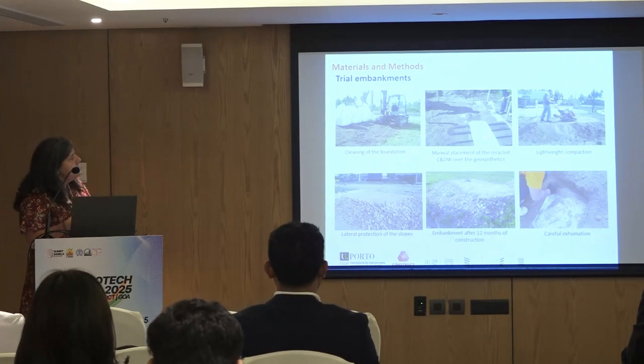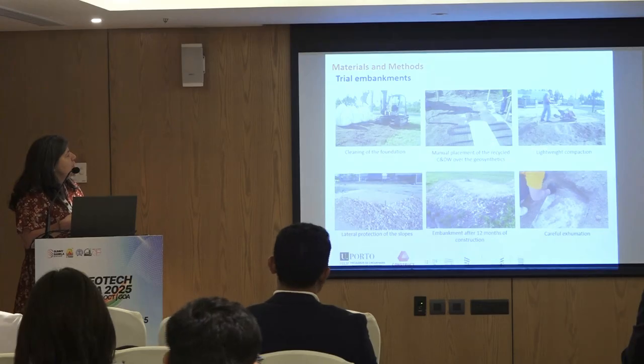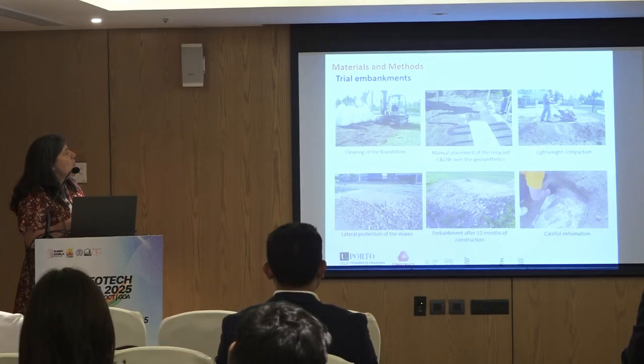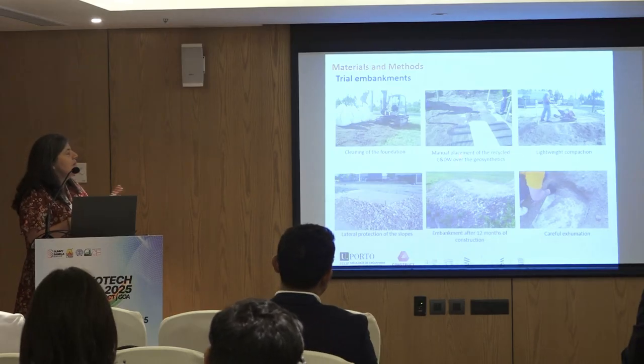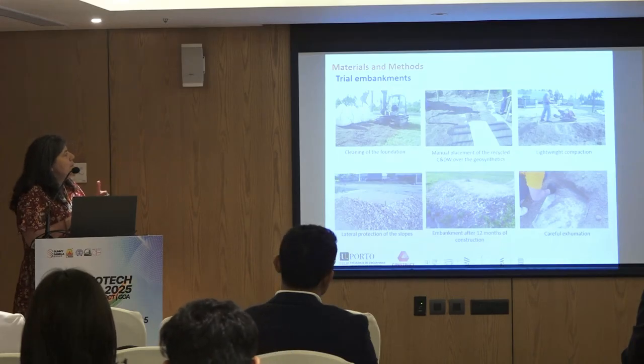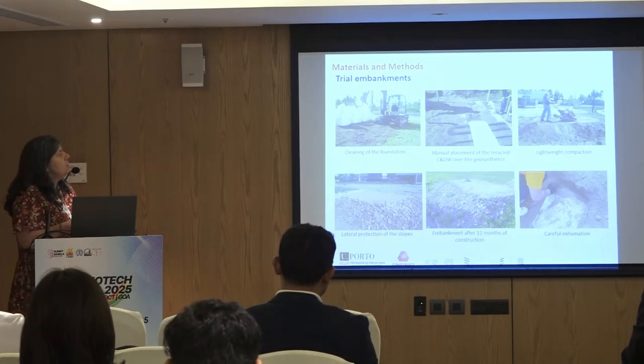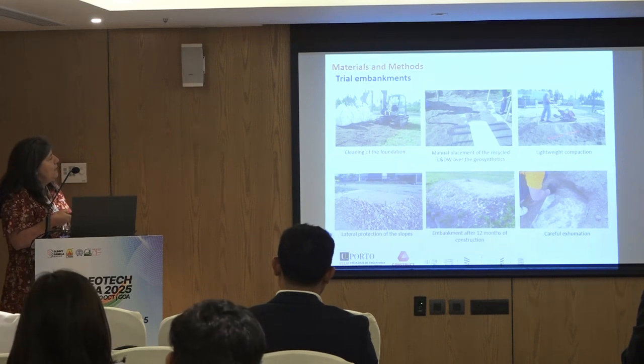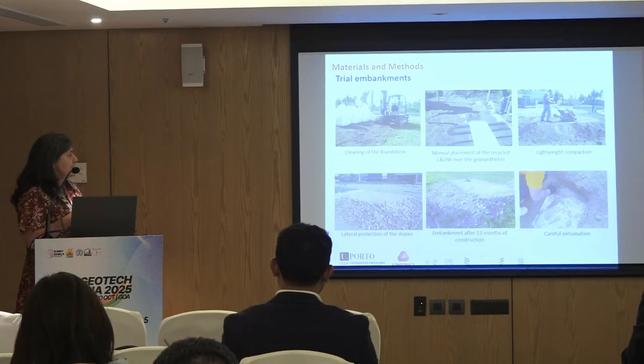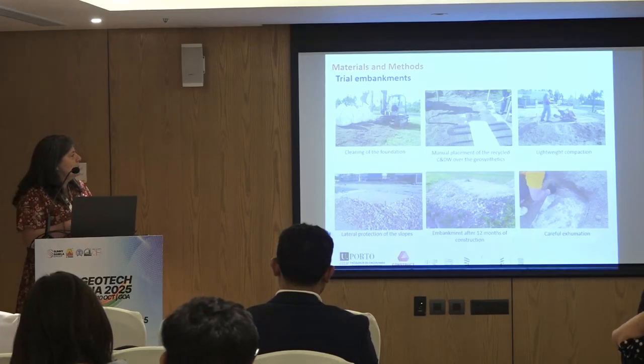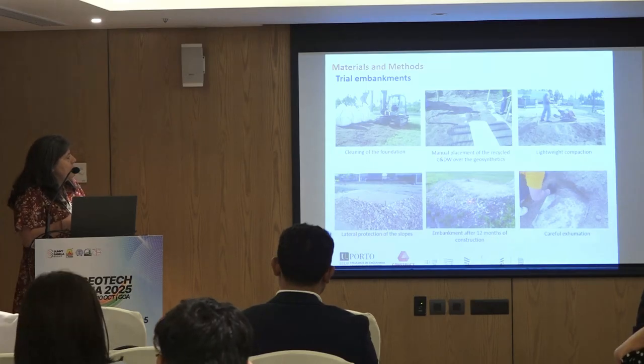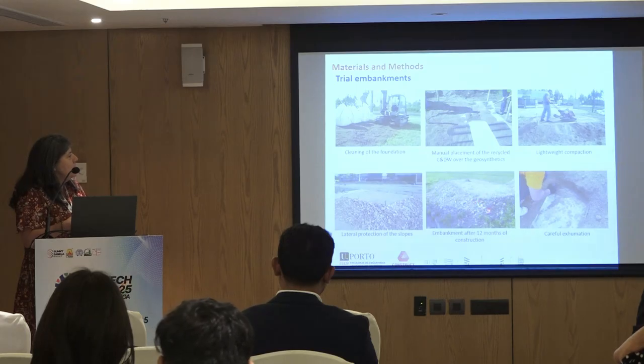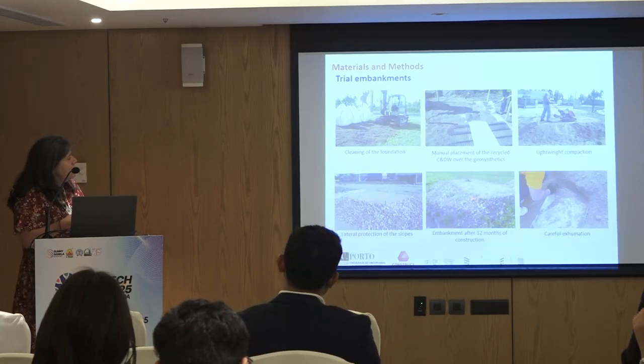This slide shows the different steps of the construction of the embankments: the cleaning of the foundation and the manual placement of the fill materials, in this case the recycled aggregate or the natural soil. The fill material was placed with care to avoid any kind of mechanical damage during construction. Lightweight compaction was also used. Then the lateral slopes of the embankments were protected with a coarse recycled aggregate, and then we waited for some kind of degradation. Here I show a picture of the embankment after 12 months. We can see here some plants around the embankment.